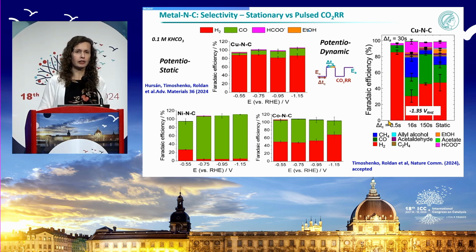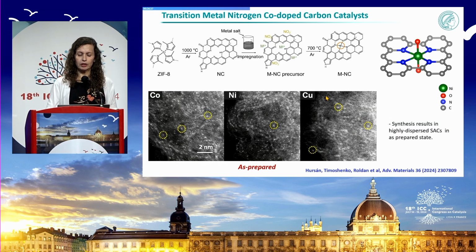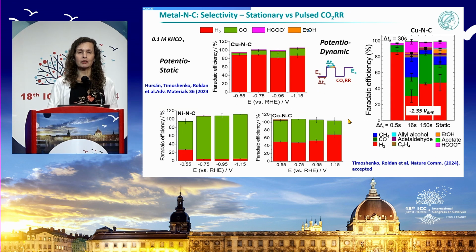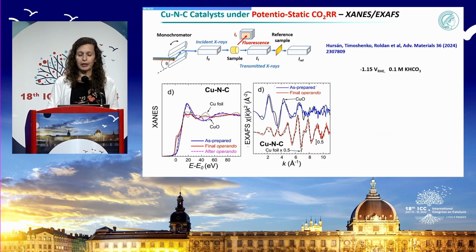Now what happened to the catalyst? If you only look at this material before and after reaction, it looks like highly dispersed copper. But it would be very strange that you can make, with these single atom catalysts, C-C coupling processes that go beyond CO. We know that this is not possible, so we try to understand how the structure of this single atom precatalyst changed.